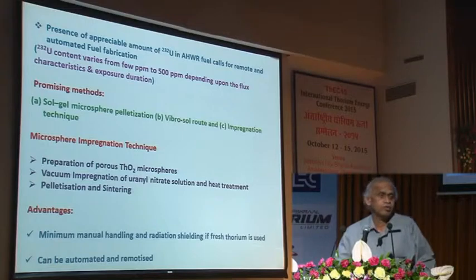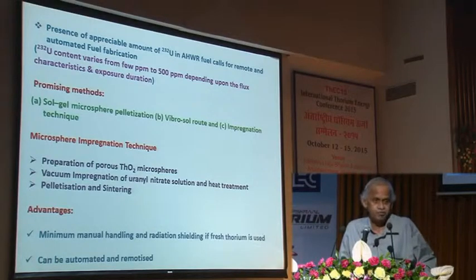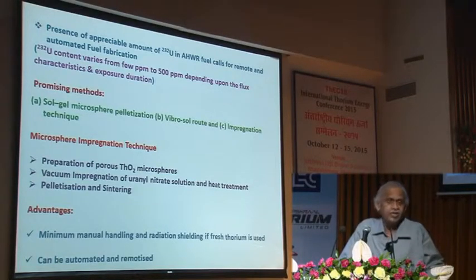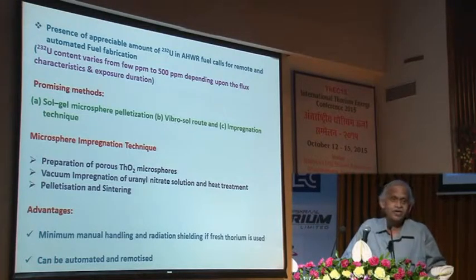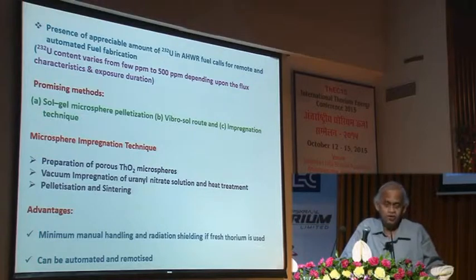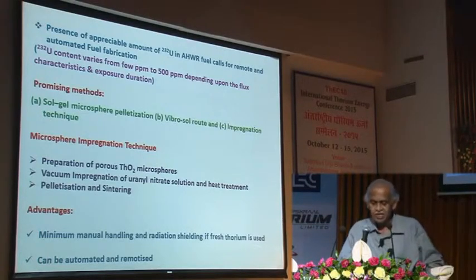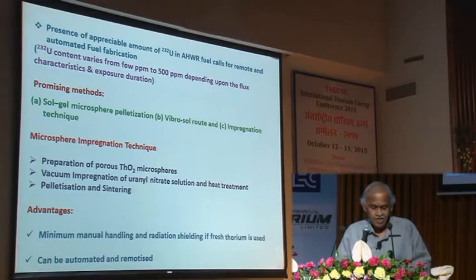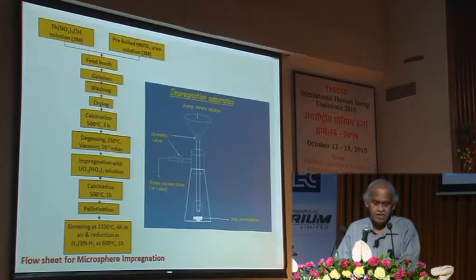The first and foremost requirement is to go for the preparation of porous thorium oxide microspheres. Then we go in for vacuum impregnation of uranyl nitrate solution, and after heat treatment we go for pelletization and sintering. Of course, the advantage is I need not have complete shielding facilities. I can go only for the minimum manual handling and of course radiation shielding if fresh thorium is used. And it can be really automated and remotized.